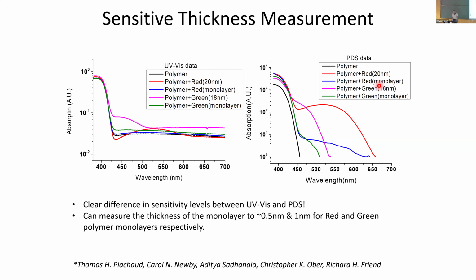You put the same sample in PDS. What you see is the red curve showing the 20 nm absorption here, and the supposed monolayer is down here. Absorption scales linearly with thickness, so essentially you know the thickness of the sample you're investigating.